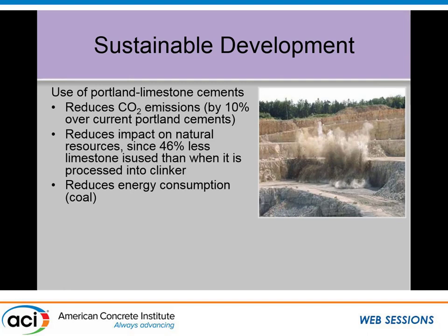And not only do you reduce cement, you can reduce the CO2 footprint of the cement produced by about 10%. It also reduces the amount of limestone you need to quarry because you're not sending half of it up into the air as CO2 gas. So you can actually extend the life of the quarry at the cement plant. And it reduces the energy consumption as well to produce cement. So there's a whole bunch of good things that are obtained by using the limestone cement.